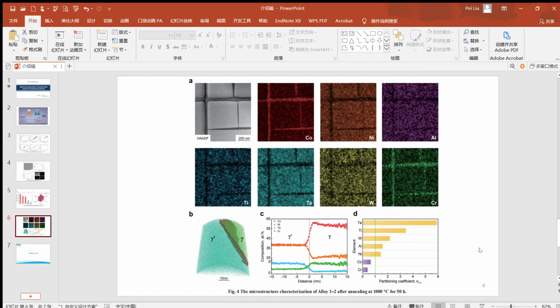This result of partitioning coefficients demonstrates the black box machine learning models could detect the inner partitioning mechanism of each element and provide active guidance in optimization of multiple properties and combinations. Comparing the cobalt and nickel contents in the two phases, cobalt is the major element of the gamma matrix, followed by nickel. While the contents are nearly equal in the gamma-prime phase, the higher nickel content in the alloy expands the gamma-gamma-prime two-phase field and increases the stability of the alloy, which is clearly captured by the machine learning approach. It also suggests that the future research direction is likely the design of nickel-rich cobalt-based superalloys, also known as cobalt-nickel-based superalloys, with desired multiple properties.